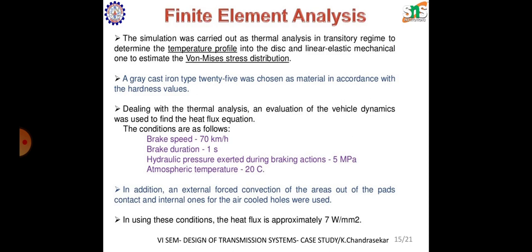Dealing with the thermal analysis, an evaluation of the vehicle dynamics was used to find the heat flux equations. So the conditions taken are a brake speed of 70 km/h, a brake duration of 1 second, a hydraulic pressure exerted during braking action of 5 megapascal, and an atmospheric temperature of 20 degrees Celsius. These are normally used in the analysis. In addition, an external forced convection of the areas outside the pads' contact and internal ones for the air-cooled holes were used. Using these conditions, the heat flux is approximately 7 watts per mm square.